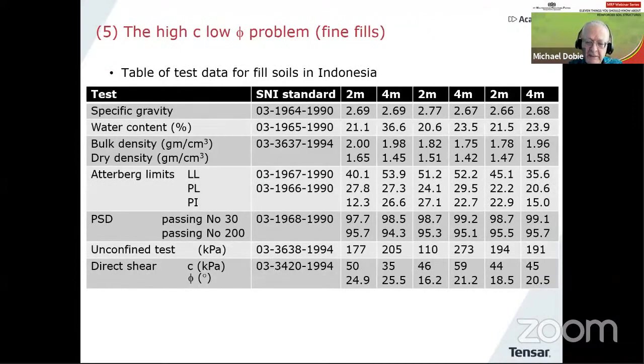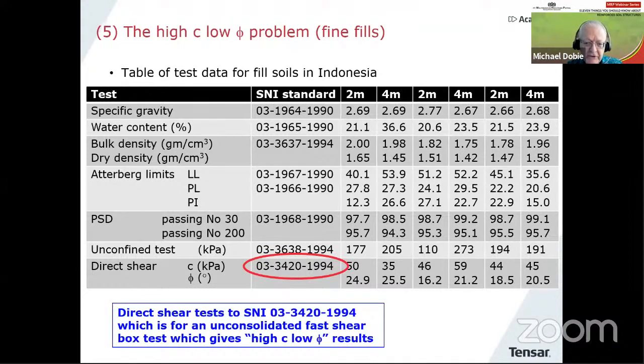Well, let's take a table of some data here. This is from a site investigation report in Indonesia many years ago that I received. You can see all the nice information here, various index properties, and all the standards are mentioned there: Atterberg limits, a summary of particle size. And then at the very bottom, we have direct shear tests. That particular SNI standard is for an unconsolidated fast shear test. So the values you see there of C and phi, these are what I call high C, low phi results.